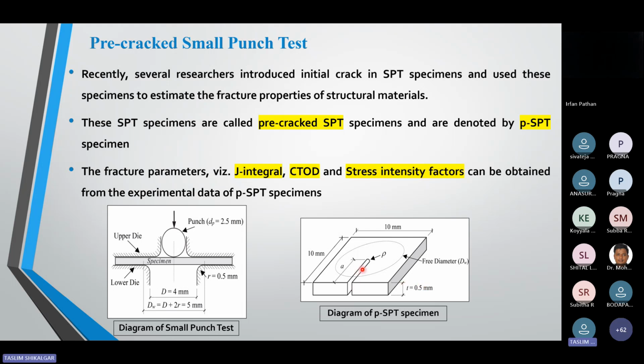Both are terminologies used in the literature. Sometimes people call it a notch, sometimes people call it a crack. But for the fracture mechanics approach, you need to call it a crack. And generating this type of crack in the specimen is a very critical part, because you cannot generate natural cracks in the specimens with the help of fatigue loading. So for this purpose, people use wire EDM or laser techniques to generate this type of cracks.